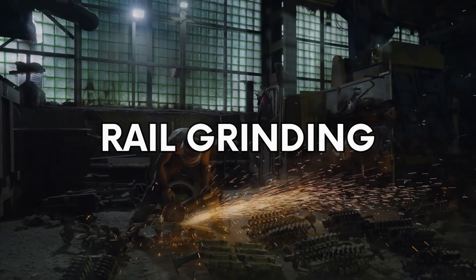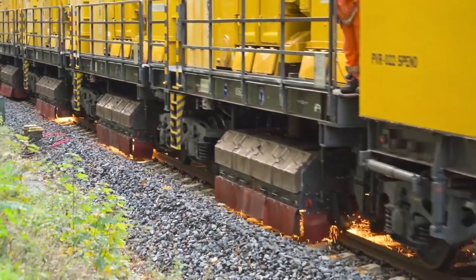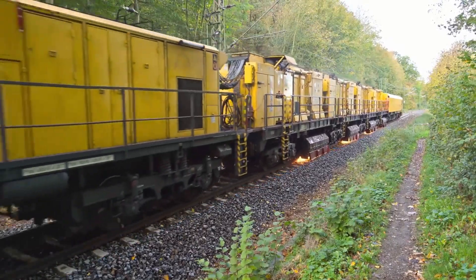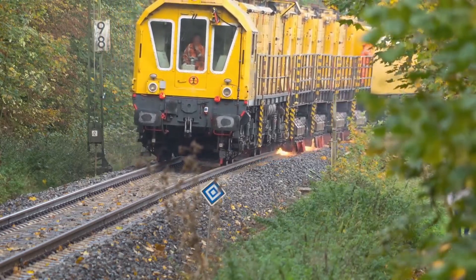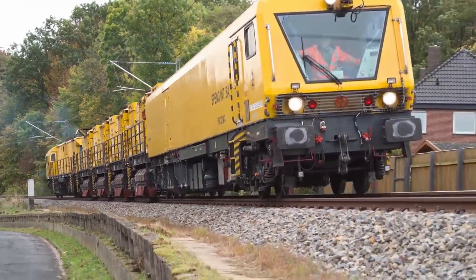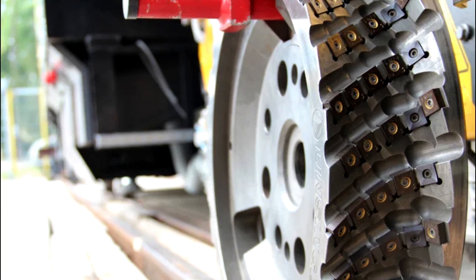The answer is rail grinding. This second option for engineers to extend the life of existing rails is very well used across the world. It involves using specifically designed trains to grind the rails back to the correct profile. The rail is reduced ever so slightly in size as grinding removes material, but it is the correct shape again. This improves the wheel-rail interaction and reduces the friction. Grinding can also remove or reduce surface defects such as RCF. High speed rail grinders can work up to 62 miles an hour or 100 kilometres an hour, although they may have to take it slower on sites with heavy wear. There is a further and more severe version known as milling, that removes even more material from the rail head and is very effective at removing deeper surface defects.